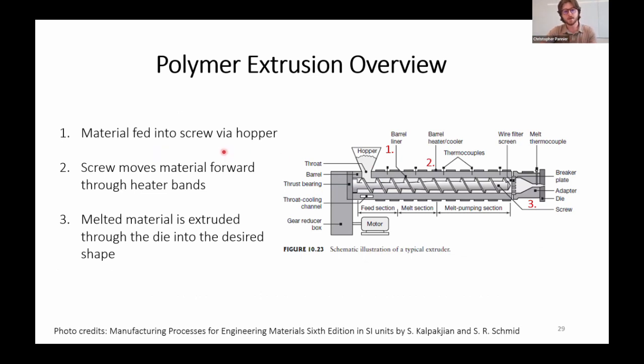In our case, the material will feed into the hopper here at number 1. That would be our shredded material or virgin material, depending on what we're working with. That shredded recycled material would be very similar to what Dawood had talked about in his presentation. Then the material is fed through the center here in the screw, and it moves through heater bands. These heater bands heat the material, melt it down, and allow us to extrude it at the die. In our case, we'd be extruding through the nozzles, which is our die, of a circular cross section with a goal of getting 1.75 millimeter filament that's commonly used in hobbyist printing.